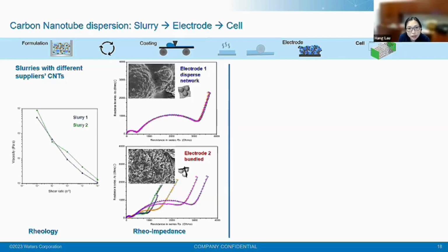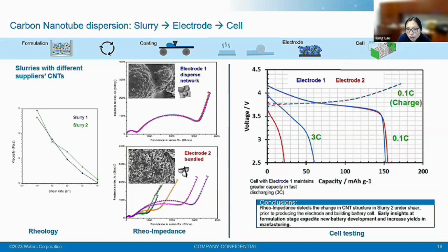We used the two types of slurry to formulate, dry them, and look at the SEM. We're seeing that the electrodes produced from the two different slurries are very different. One of them has more of a mesh conductive network. The other one is very bundled and aggregating. We did not see a really nice conductive network. Then reproducing, making a coin cell to evaluate those, we're seeing differences. For low charging rate, low C rate, 0.1 C, we didn't see much difference in capacity loss, but it's very important when you come to fast charging, when a lot of battery formulation is looking for increased fast charging.